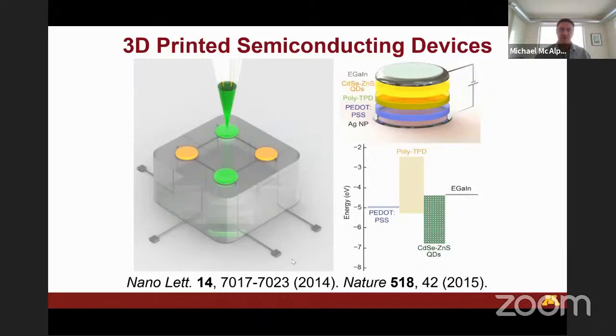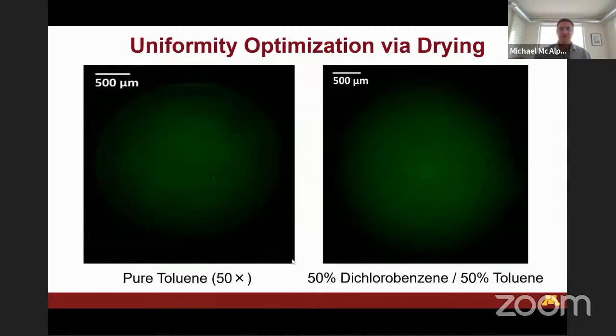We showed that by layering multiple materials, including silver nanoparticle on the bottom, and then 2 organic polymer layers for hole injection, and then a cadmium quantum dot layer as the active semiconductor layer, and then a liquid metal, which is pioneered by Michael Dickey, who also gave one of these EML webinars. We use that as our top electrode. That we can essentially create a semiconducting device where every single layer of the device, the electrodes and the semiconducting layer, are all 3D printed on the same platform. Not the world's greatest device, but it works.